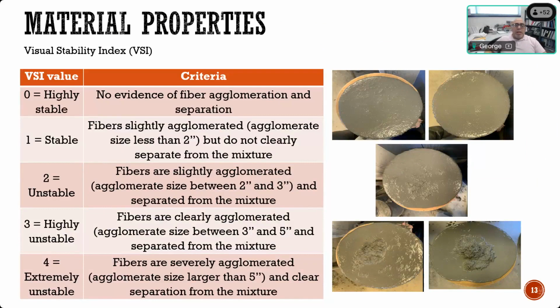There's no standard test to do that, but so far we evaluate that visually using what's called the visual stability index, by looking at the shape of the material once you do the flow test, and see if the fibers are well distributed, or if there's any separation or any kind of agglomeration in the fibers. You can see the top one here is very highly stable. That's visual stability index 0. This one has a little bit, that's considered 1. Now when it starts forming like this, that's unstable. And of course, 3 is highly unstable, and 4 is like that.